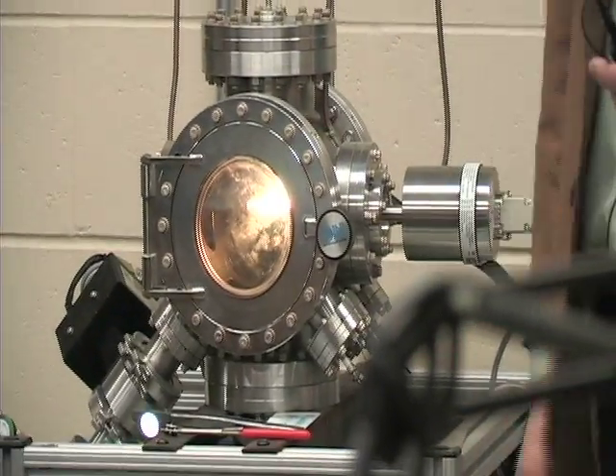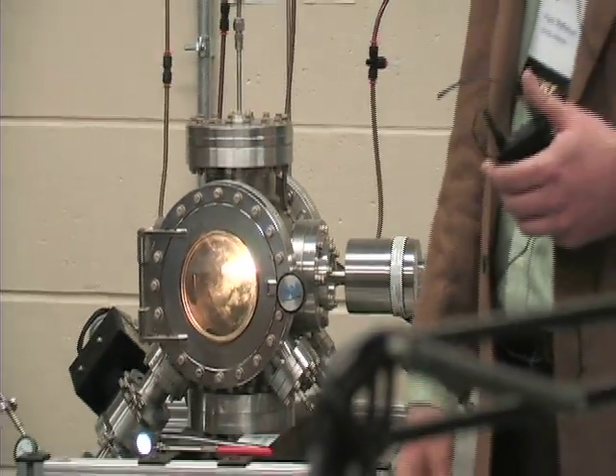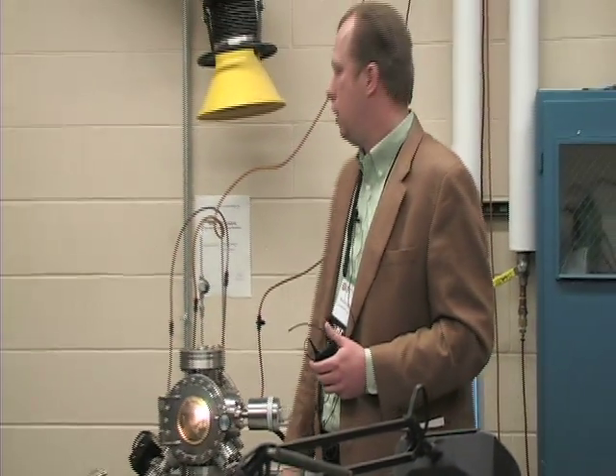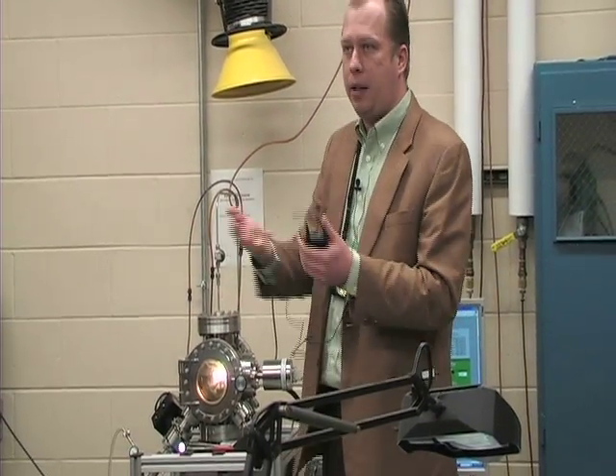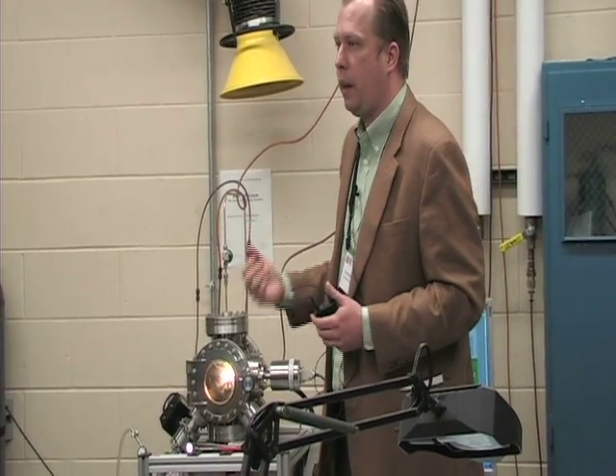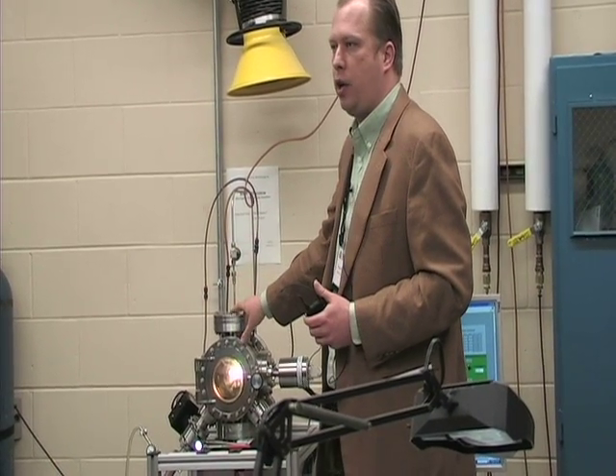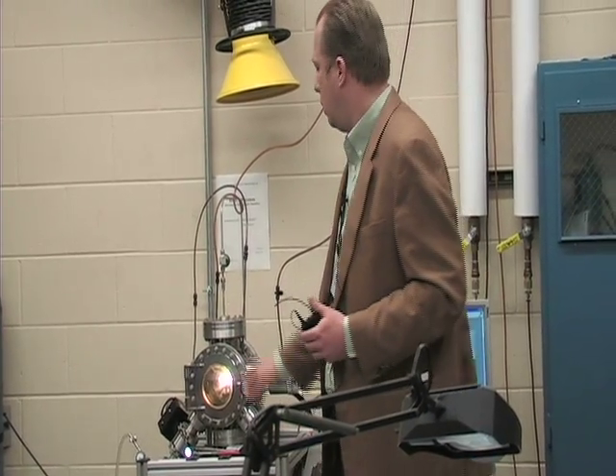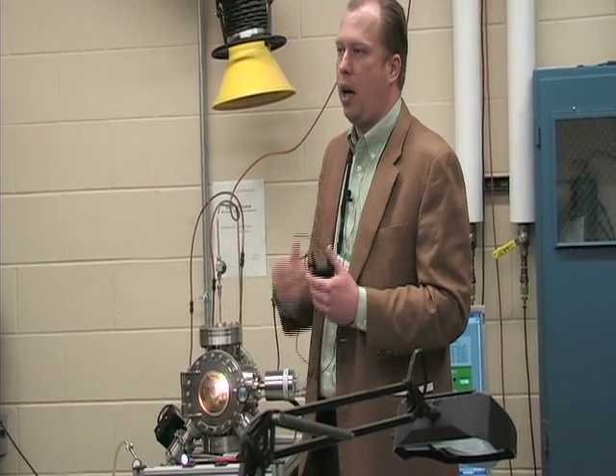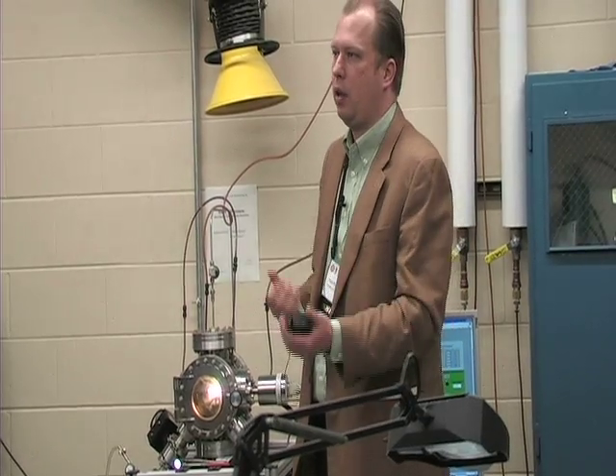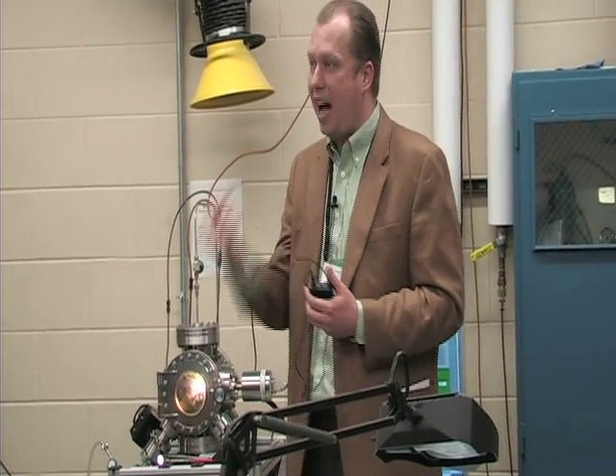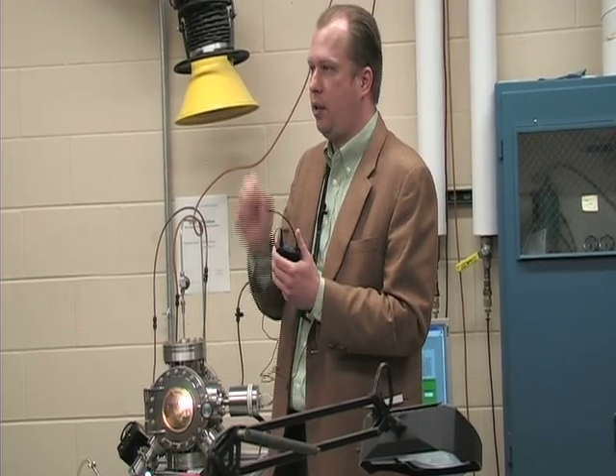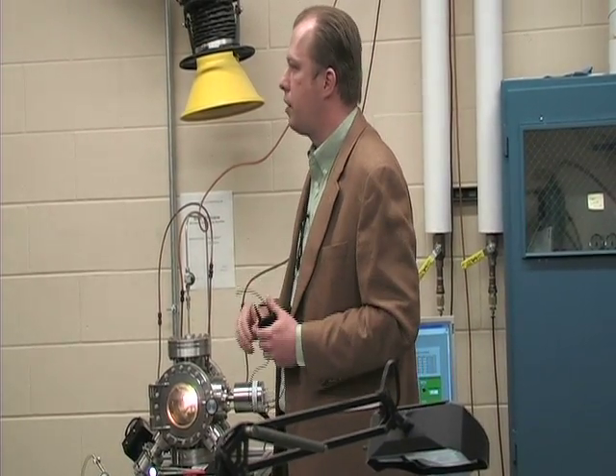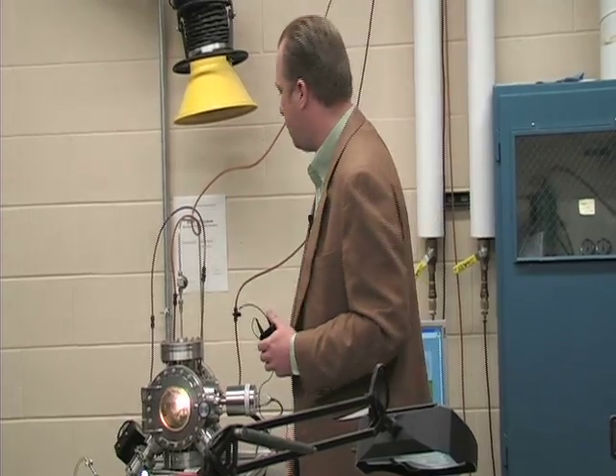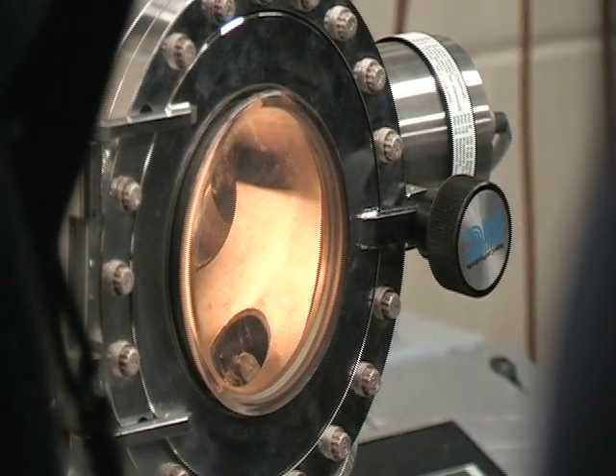Tungsten filaments, just like the old light bulbs here, we get them to about 2,000 degrees Celsius to dissociate those gases. All right. And the radiation from them heats the substrate, in this case a micro end mill, and then the gases come down under the right pressure and gas mixture conditions. When they hit the hot surface, chemical reactions occur, and ultimately what we're looking for are diamond bonds forming. And so literally it is an atom by atom process of synthesizing or growing this diamond film on the coating. So we do this in-house with our collaborators.